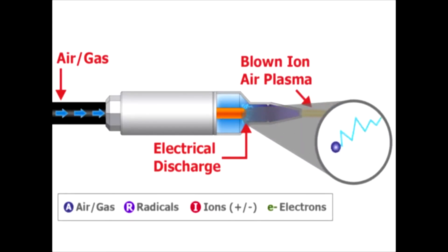The air pressure forces the air particles to accelerate out the tip of the head as a high velocity stream of charged ions directed towards the substrate surface. Through direct contact, these particles positively charge the object surface, increasing its surface energy and making it more receptive to inks and coatings.